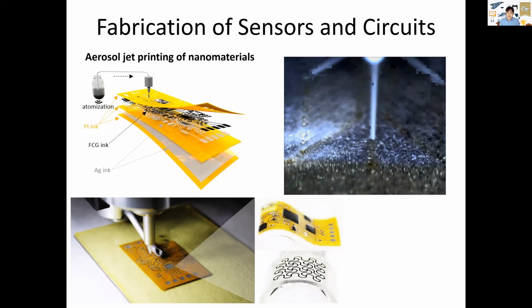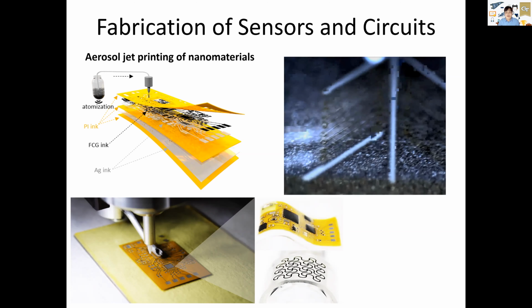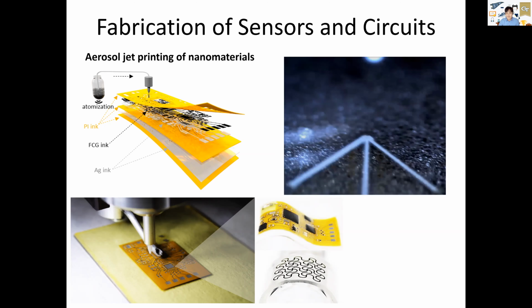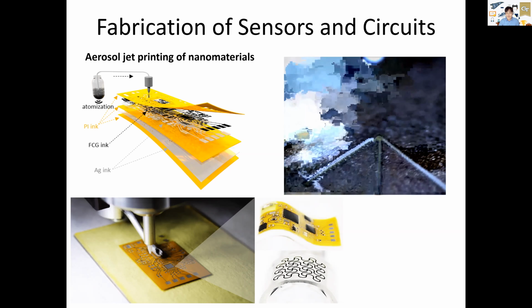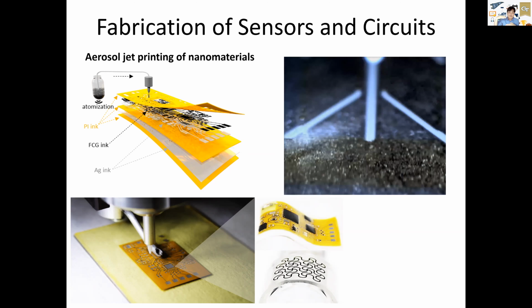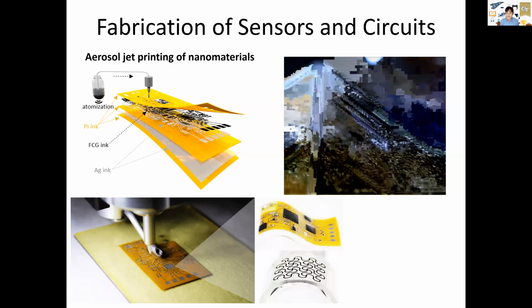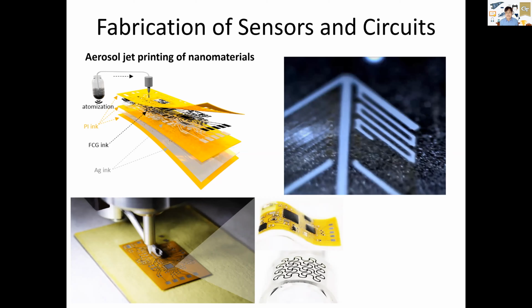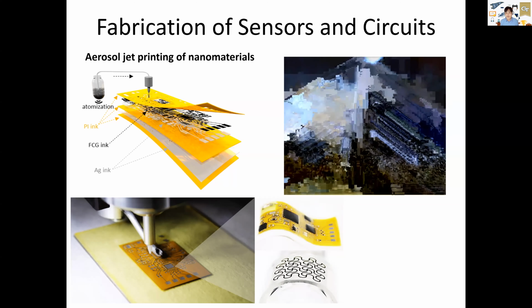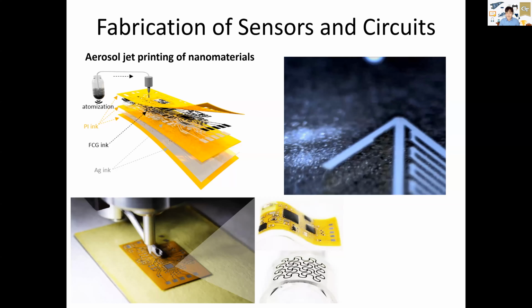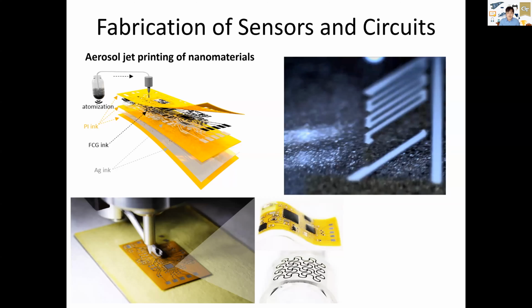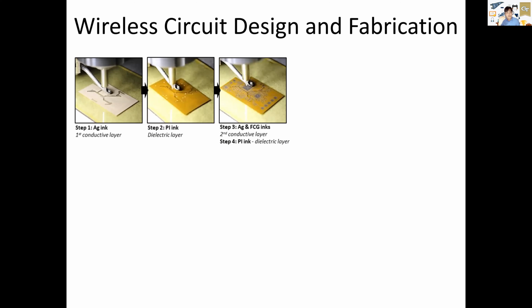Right now, there's a little nozzle on top of that, and it's shooting silver nanoparticles. So it's basically drawing a nanomembrane sensor. It's called aerosol jet printing. The major advantage of this method is that it has a really large working distance between the nozzle and substrate. And also, this printing method can handle various types of inks, from metal to semiconductor, polymer, and even biological solutions. So it's covering viscosity ranges from 1 to 10,000 centipoise. Based on this aerosol jet printing technique, we can print sensors and also circuit interconnects.